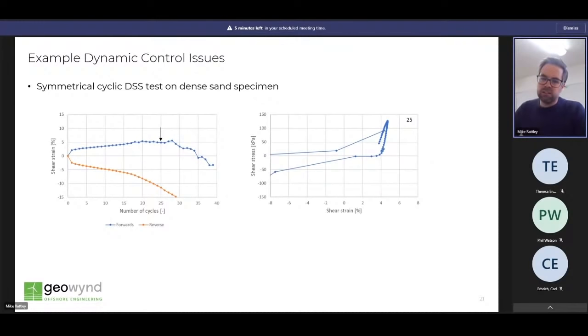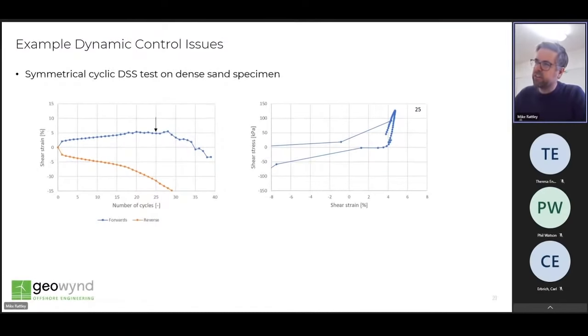So really digging into the cyclic data and taking a look at that on a cycle basis, because this is valid perhaps up to only about 7 to 8 cycles and to a limiting strain of around 4%, which coincides quite conveniently with that onset of the temporary liquefaction response, which drives that loss of stiffness through the reversal.